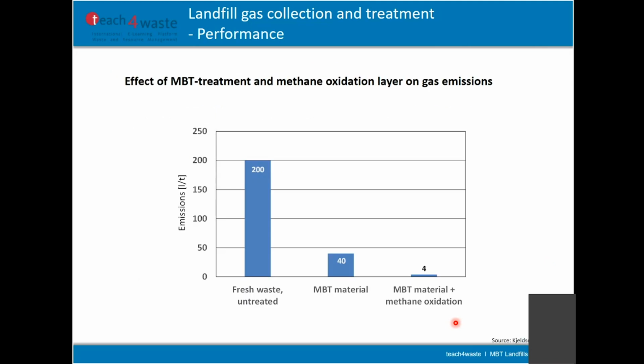So the performance of methane oxidation is very good, as you can see. Here is the emission potential. If you have fresh waste, roundabout 200 liter per ton. It's depending on the composition as always, but here a mean value of 200 liter per ton. By MBT, we are reducing this big amount to about 40 liter per ton. And if we place this material below such a methane oxidation layer and make a measurement on the top, then maybe we get 4 liter per ton of remaining gas potential. So this is very, very low.